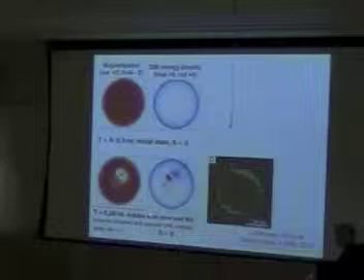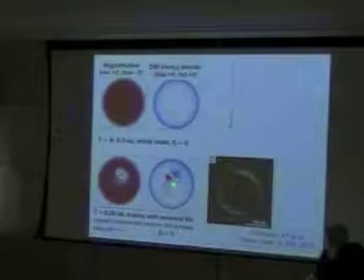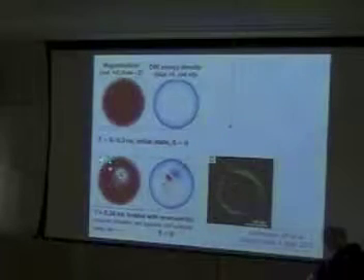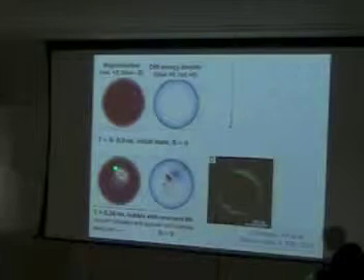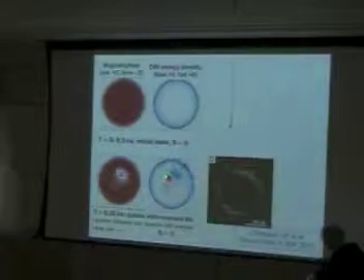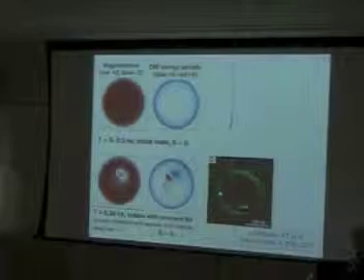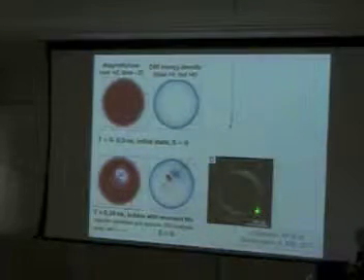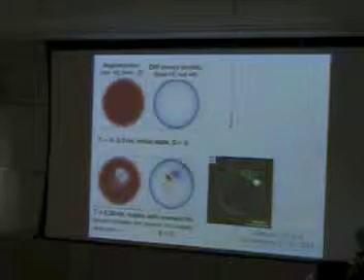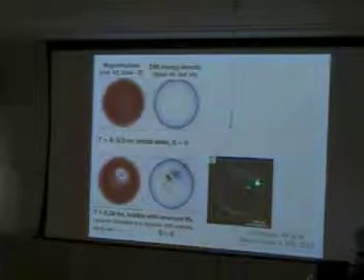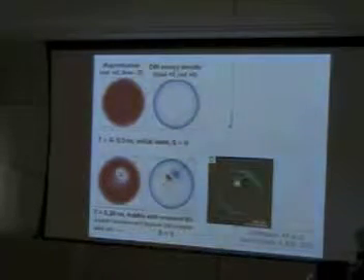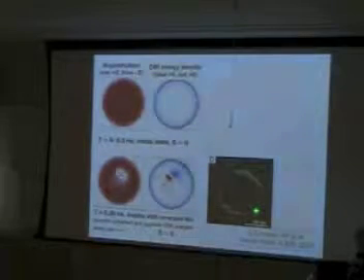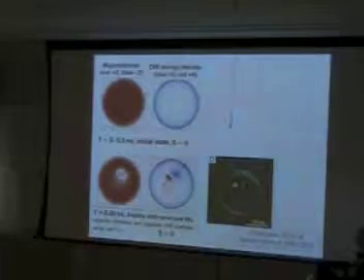In fact, in between, there are two domain walls with opposite chirality, on this side and on this side. This corresponds to the classical picture for a hard bubble, with different chirality for the domain walls on both sides, and in the middle, at this point, what was called a Bloch line.